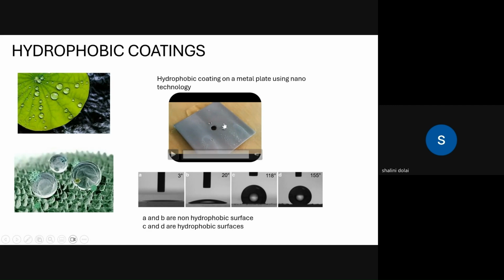So using nanotechnology, we developed a similar kind of coating in the lab where the surface became hydrophobic. If the substrate is not coming in contact with water, dust or anything, it becomes corrosion resistant. So how were we measuring whether the substrate is hydrophobic or not? We were using an optical camera, and this is a water droplet. If the surface tension is very high, it spreads on the surface. And as the surface tension reduces, it starts forming like a bead. So in this particular coating, we achieved 155 degrees of contact angle, which is a very good hydrophobic surface.